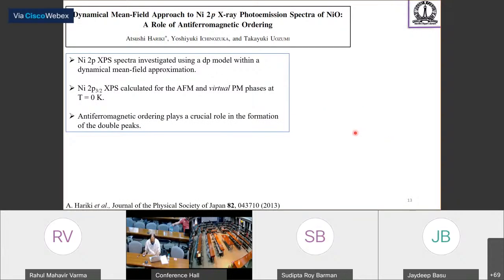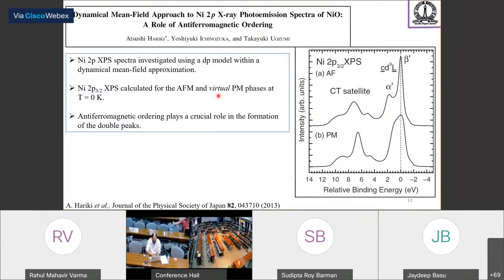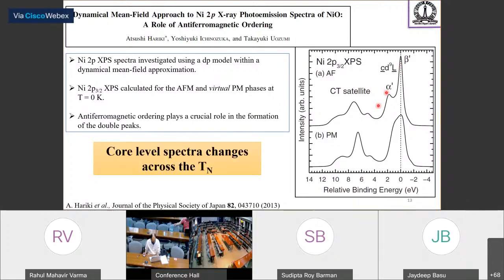In 2013, Hariki et al. investigated nickel 2p XPS spectra using the DP model and simulated a nickel 3d and oxygen 2p electron system within the dynamical mean field approximation. They calculated the nickel 2p XPS spectra in antiferromagnetic and virtual paramagnetic phases at T equals 0, and claim that antiferromagnetism does play a crucial role in the formation of this double peak, showing that the core level spectra change across the transition temperature.